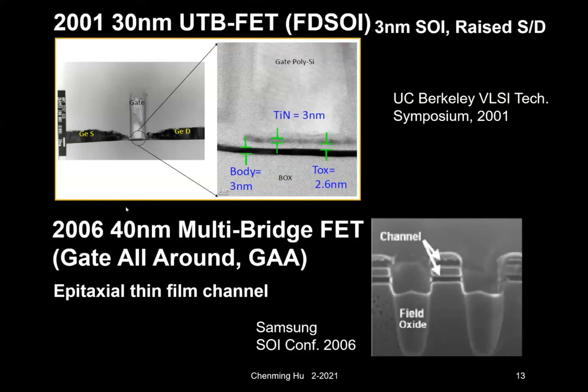And in 2006, Samsung demonstrated another way to make a thin body. In this case, it uses epitaxial thin film. So they use a clever idea of epitaxially growing a few nanometers of silicon, then some sacrificial epitaxial silicon germanium, then a very thin silicon channel. And after that, they will etch away the sacrificial silicon germanium and use this very thin silicon film as the thin body to make the transistor.